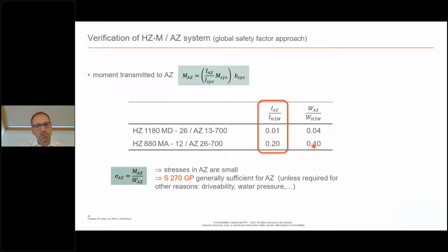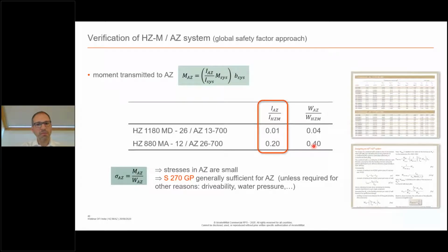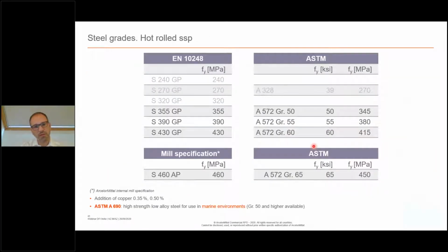What you can also deduce from these assumptions and from these results is that usually the infill sheet pile doesn't need to have a very high yield strength. So generally an S270 GP would be sufficient, unless you need it for driving reasons, if you're driving into very compact soils, or for water pressure reasons, as you'll see in one of the other slides. So all this information you can find in our brochure. You can also find in the brochure of other manufacturers, because this is the essential data that you need in order to design a sheet pile wall.